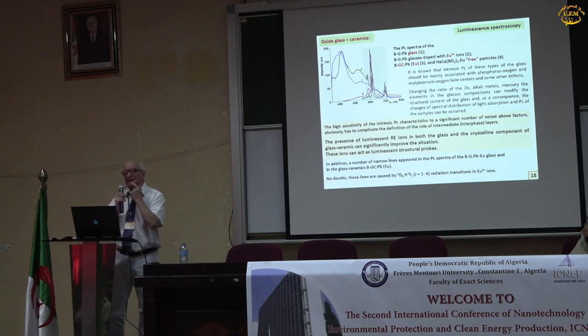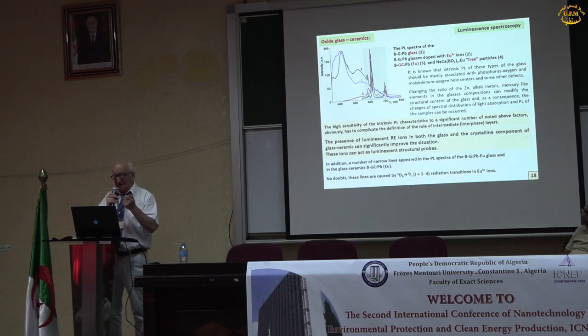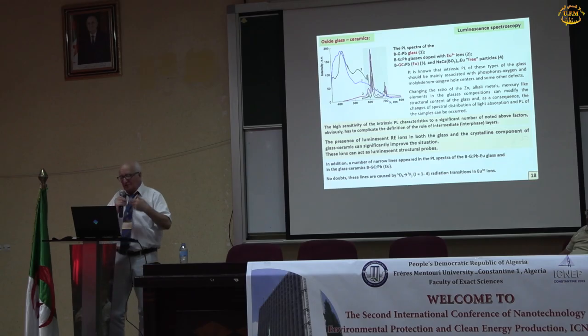As compared with study of interfaces in metallic or semiconductor composite, it is very difficult to study these layers in dielectric materials. You know, the problems. As dielectric accumulates the electrons from the electronic microscope, so the resolution of this image is low. When we cover the dielectric by metal for higher resolution obtaining, we lost the information about interfaces. So we developed the luminescence method of identification of interfaces.